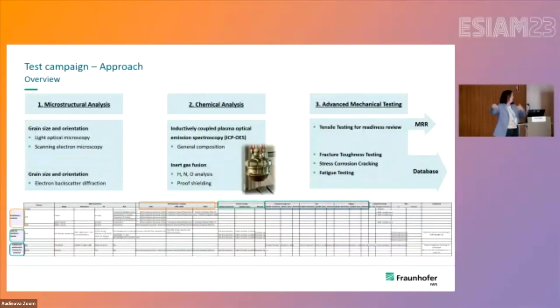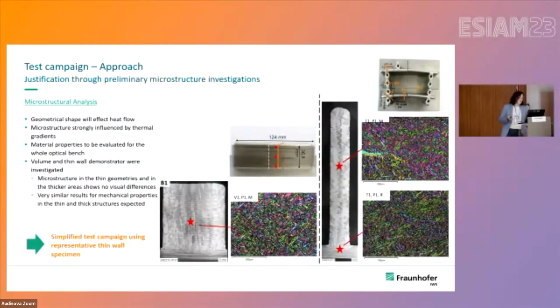The structural integrity is obviously an issue, so we had test campaigns related to the optical bench. We cannot print the whole part and then test it, but we have been aiming for a representative geometry that we can print easily and then test all of these properties you can see here: grain size and orientation, tensile testing, fracture toughness testing, and fatigue. We came up with the idea of having thinner and thicker walls to study the effect of the heat flow. It is expected that we have a different microstructure strongly influenced by thermal gradients, and therefore we started with thinner and thicker demonstrators.